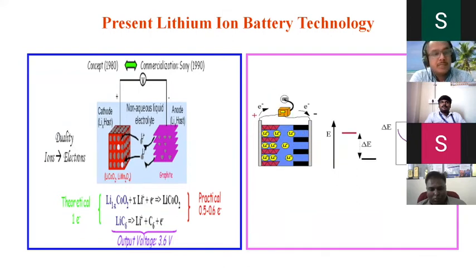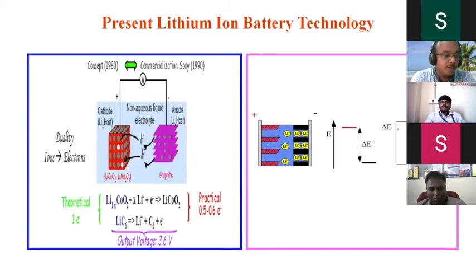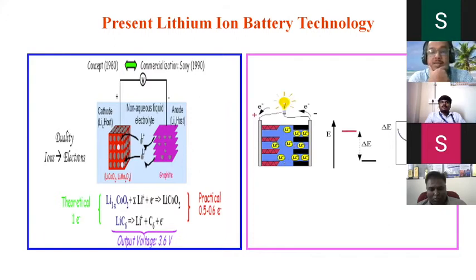If you look into the present lithium-ion battery technology and the commercialized products, more or less they are very similar to these ones. Maybe they will change a little amount of the composition of the electrolytes, or reduce the thickness of the separators, or make slight changes. Maybe instead of lithium cobalt oxide, people have gone to lithium iron phosphate or NMC, NCA or something else. But the chemistry is almost the same from 1980 to 2020, almost 40 years. There's no dramatic change in the chemistry behind the present lithium-ion battery technology.